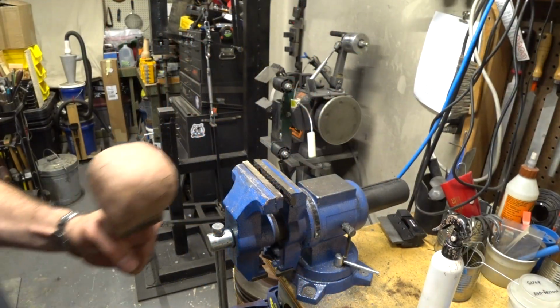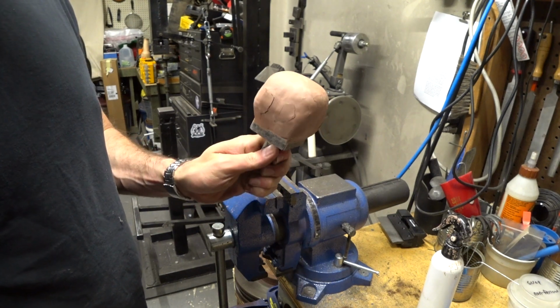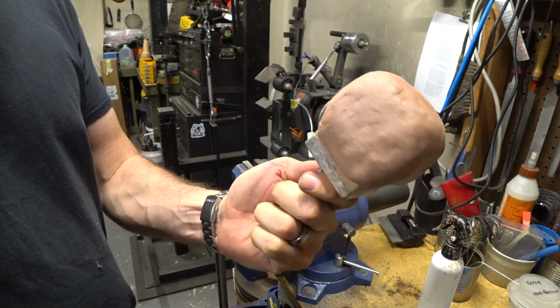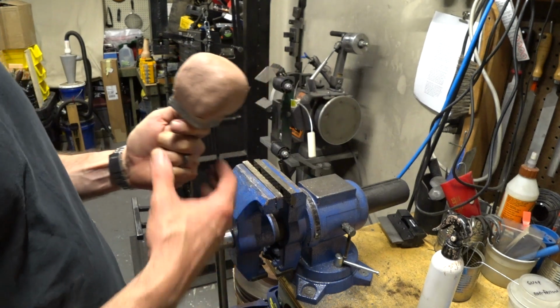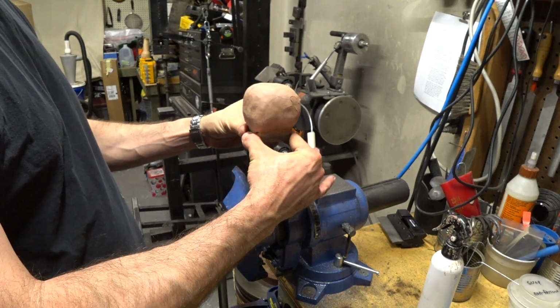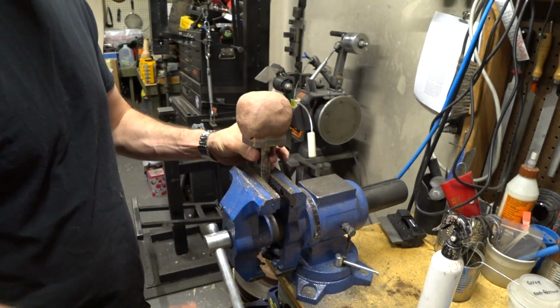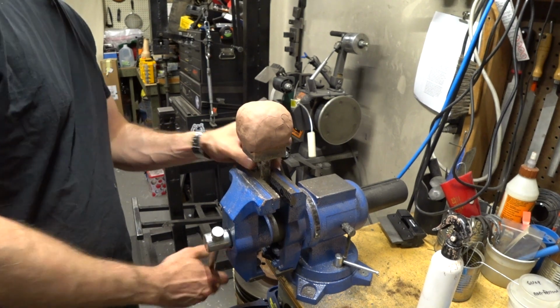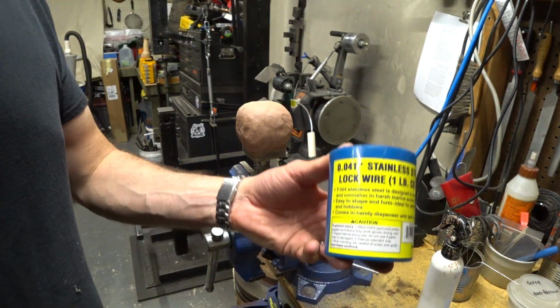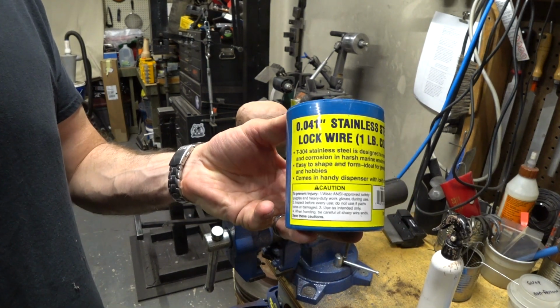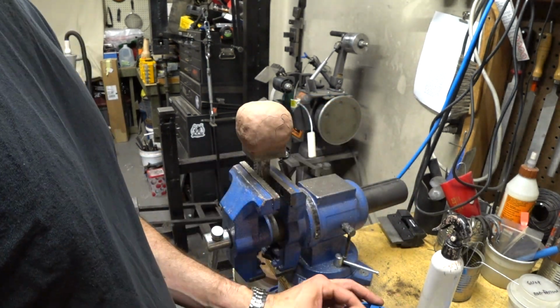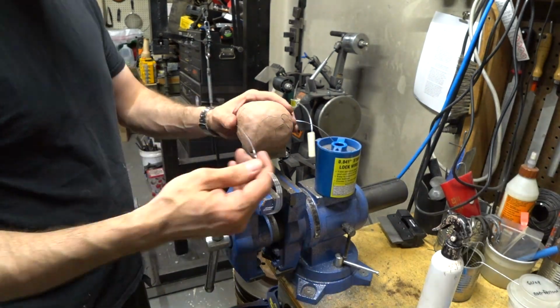So here you can see after everything's all dried up, there's still just a little bit of very small micro cracking, but that's just on the surface. As long as you have a fairly good seal, it should work good enough. So we're just about ready to actually do the case hardening procedure. I'm just going to wrap it in some stainless steel lock wire in order to help hold the clay layer on there as we fire it.